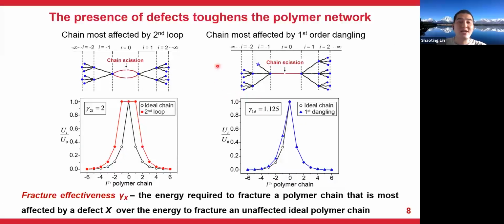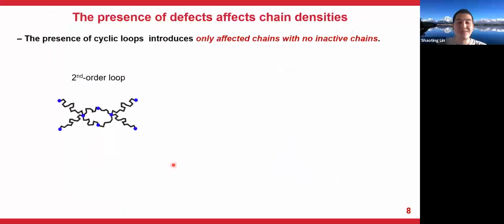We next calculate the energy relaxed by the chain affected by the second loop and affected by first order dangling chain as 2 representative examples. Both energies are higher than that of an ideal polymer chain, which indicates the toughening effect due to the presence of defects. Here we introduce a quantity gamma x to quantify the toughening effect due to the presence of defect x. Gamma x is a dimensionless parameter greater than or equal to 1. If it is an ideal polymer chain, it is just equal to 1. Otherwise, it's greater than 1.